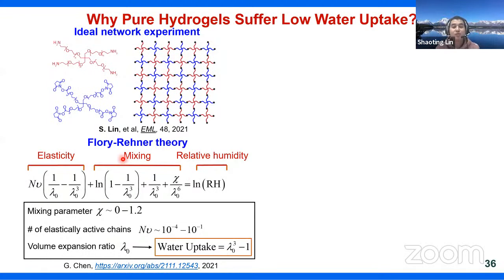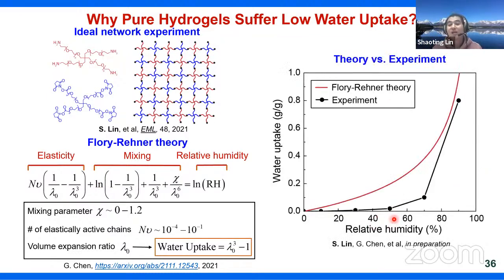So basically, there are two physical processes. One is the mixing between the polymer and the water. This is the driving force, right? It's a favorable term for achieving this high water uptake. But on the other hand, due to the swelling, due to the stretching of the polymer network, the elasticity of the polymer chains is the penalty that suppresses the water uptake. So these two eventually determine the sorption capacity at a given relative humidity level.